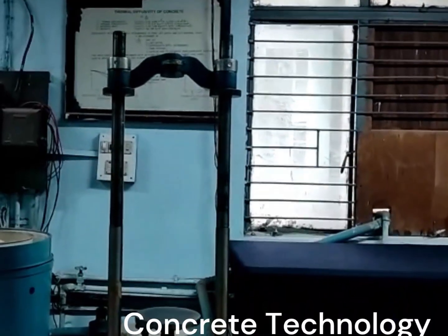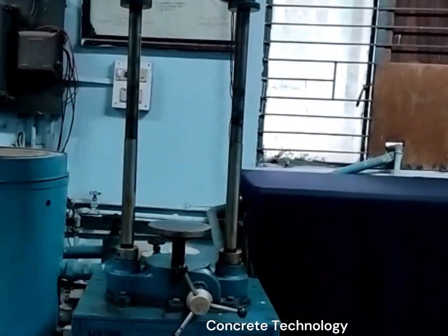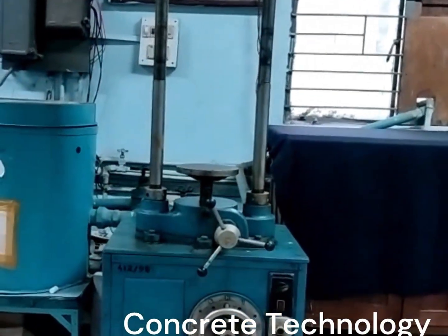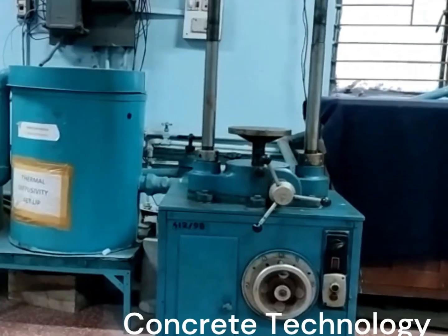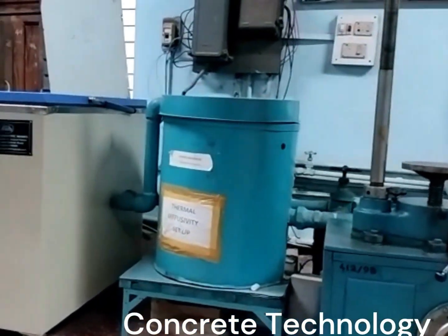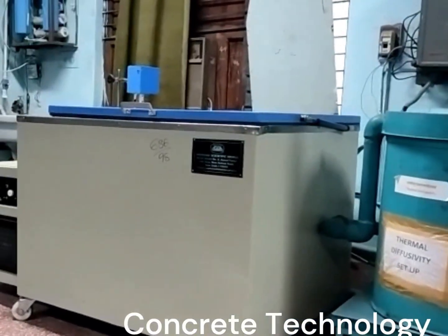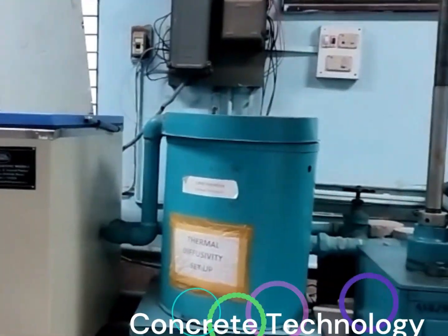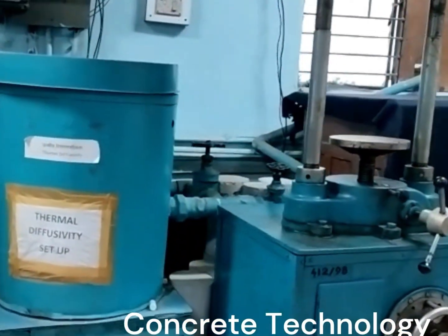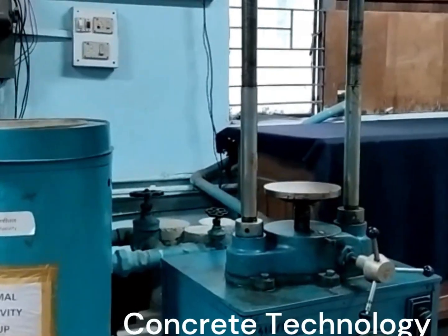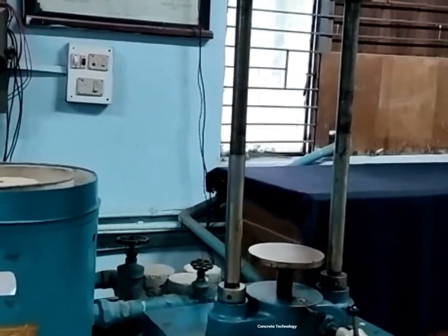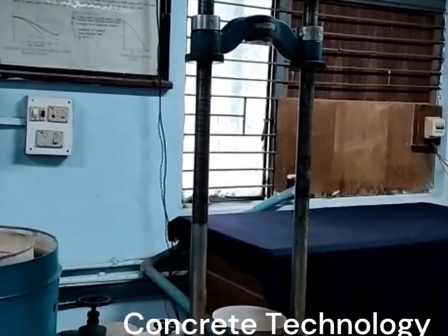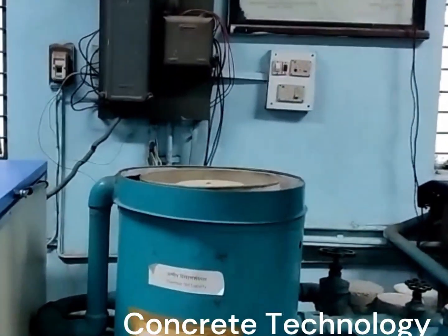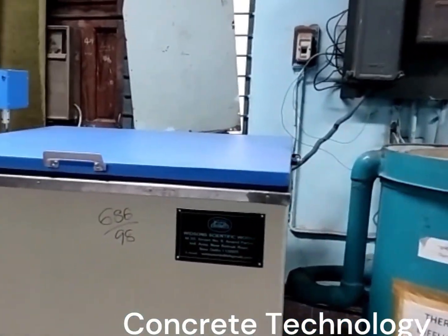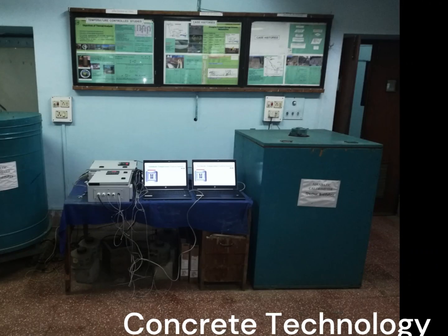6. Thermal diffusivity. Diffusivity is an index of the facility with which concrete diffuses heat in all directions. The equipment consists of hot water bath, in which water is heated through immersed heater. Cured concrete specimen is placed in the water bath at room temperature. The water in the bath is then heated to a certain temperature so that concrete sample is heated up sufficiently without cracking. The specimen is allowed to saturate in the hot water. After achieving saturation, hot water is flushed out and cold water is let in. The temperature in the interior of specimen is recorded at every 5 minutes interval up to a period of 1 hour. From this data, cooling history of the concrete specimen is obtained.